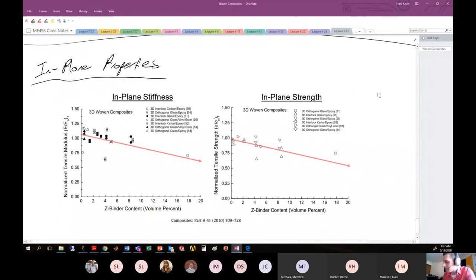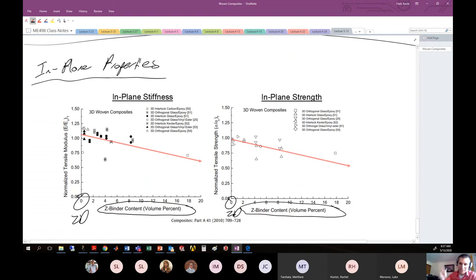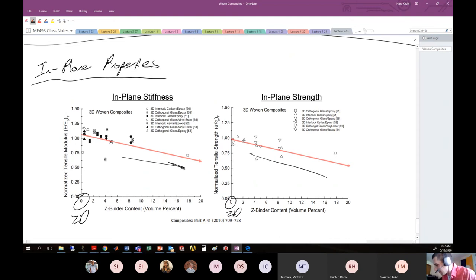Okay. So what you see here is when we're in the 2D case with 0% Z binder, you have some baseline level of, let's say, the elastic modulus or baseline level of the tensile strength. All right. So a normalized value of 1 in both situations. As you start adding Z binders to the 3D woven structure, right, more and more density of these through thickness Z-tows, you start to see general reductions in the property. All right, so we see this arrow making its way down. And with very high levels of Z-binder content, you can reduce strength by like 75%, reduce stiffness by 60%, so on and so forth. So incorporating more of these Z-binders, you're eliminating the amount of tows that are just running directly in the plane. So you're reducing your mechanical properties based on the amount of Z-binders that you incorporate, sort of in this linear fashion. So maybe not exactly linear, but I've kind of drawn a linear line in here.